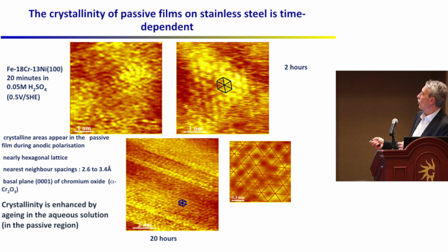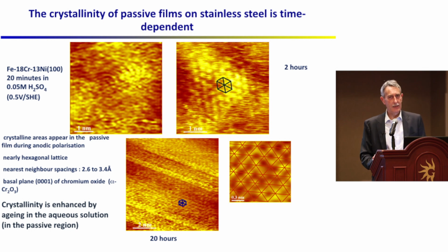This is completely disordered. You start to see these nanocrystals in the passive layer, and then at the end it's very well crystallized, so that crystallinity takes time. And then we looked at the stability. So we produced these passive layers, and after some time introduced chlorides, and it was clear that the more crystallized, the more corrosion resistant was the oxide layer.